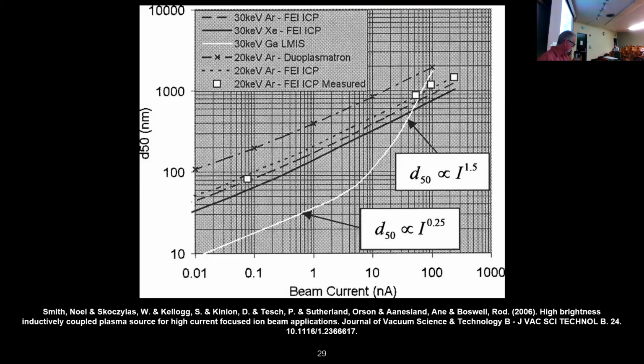Now into my favorite beam, the ion beam. So this chart is from Noel Smith. He was at FEI at the time, now he's at Oregon Physics. The things we really want to look at here are the white line and the solid black line. The white line is the resolution of a gallium FIB. Keep in mind, this paper was done in 2006, so it's nearly 18 years old now. And the black line would be an inductively coupled plasma FIB. And we can see at very low probe currents, there's a big advantage to gallium.